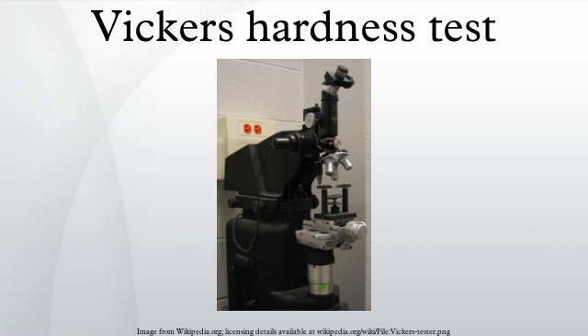When doing the hardness tests, the minimum distance between indentations and the distance from the indentation to the edge of the specimen must be taken into account to avoid interaction between the work-hardened regions and effects of the edge. These minimum distances are different for ISO 6507-1 and ASTM E384 standards. Estimating tensile strength, if HV is expressed in the appropriate units, the tensile strength of the material can be approximated as, where C is a constant determined by geometrical factors usually ranging between 2 and 4.